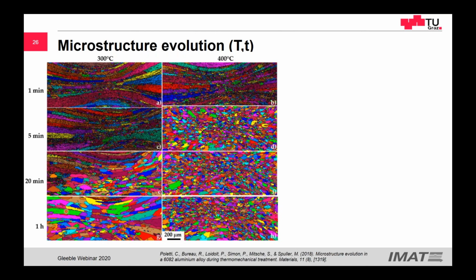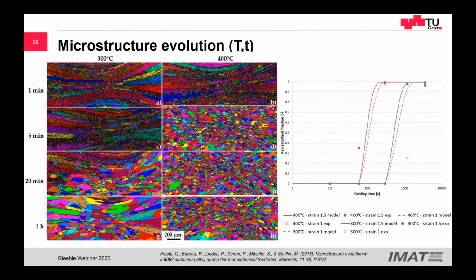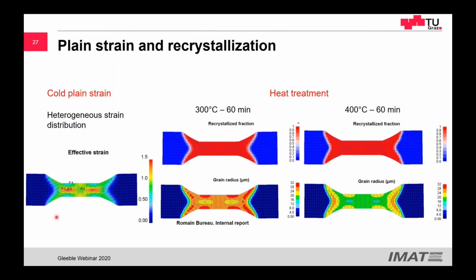We also have seen that at low temperatures, so at 300s, the grains grow very slowly and from some nucleations, they grow with a form like this, and this shape is coming from the large precipitates, large aluminates, that pin the grain boundary movement. So very nice to see. We managed to put this in the model, and with this we could also get the recrystallization fraction and the grain size that we implemented in finite element simulations. So of course this is only for one sample, but this can be translated into large rolling parts. So you get the recrystallization fraction as a function of holding time and also the grain radius, the grain size.